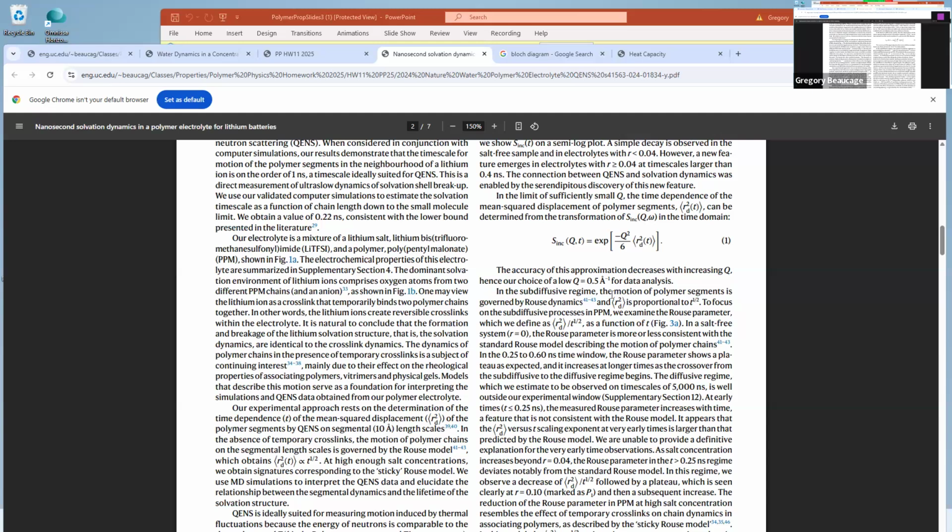But basically, he's going to 0.5 because he thinks that's the size of a monomer. So it's like a resolution. Like you're looking at the motion of things, what things are you looking at, and you want to pick a size that's the size of those things. So if you wanted to look at the size of this room, you do 2 pi over whatever the size of the room is, and you go to that Q. You know, but if it's a monomer, it's 10 angstrom. He claims that. So that's the Q that he goes to look at monomers moving.